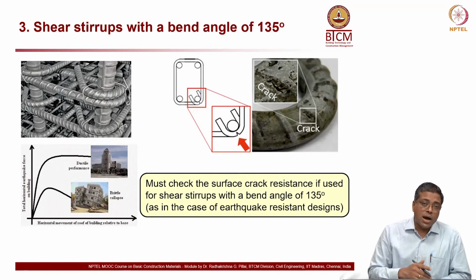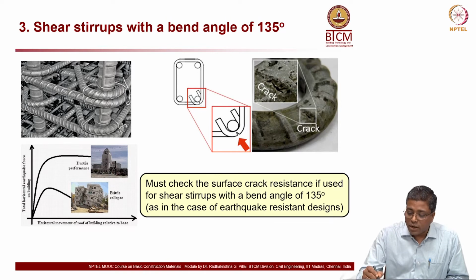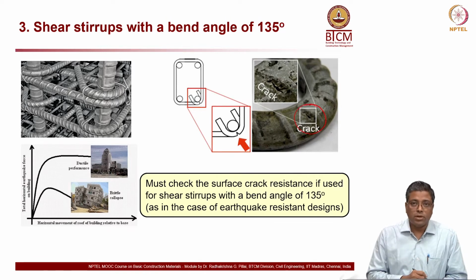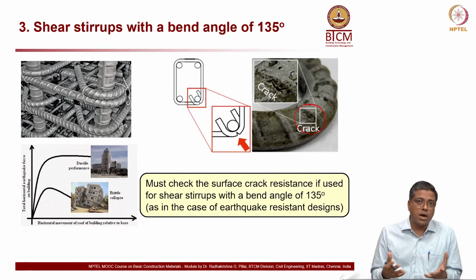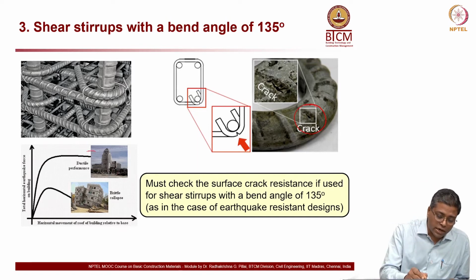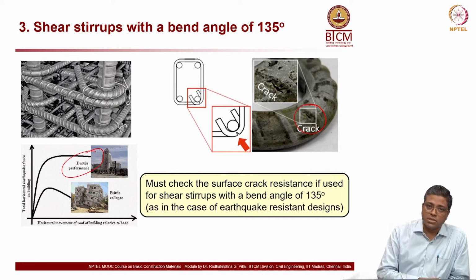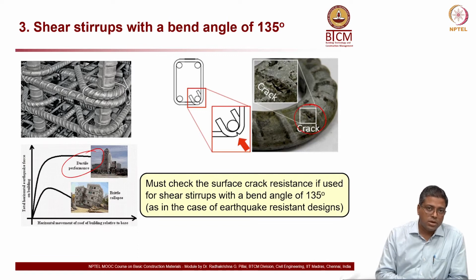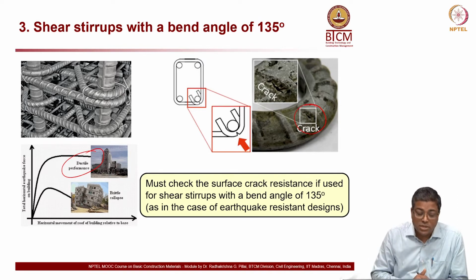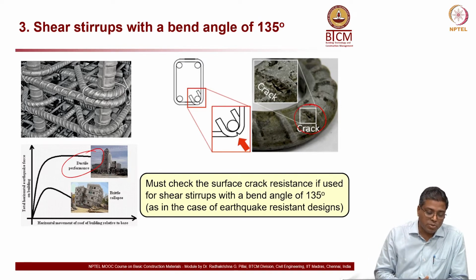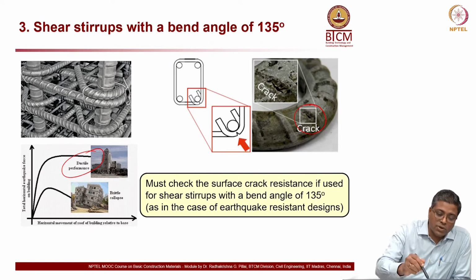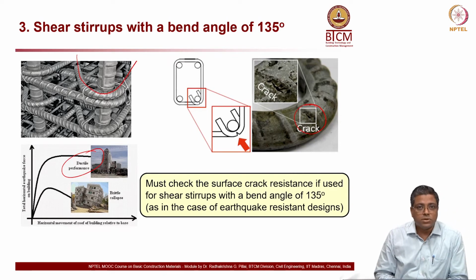Now we bend the bars at the site, and while bending, this kind of crack should not happen. Why do we use this bar? We use this bar for getting ductile performance for our structures. That is why we use TMT bars. The core region is more ductile, I told you, ferrite pearlite is more ductile. The peripheral region gives you the strength, which is tempered martensite. So the ductility is the key thing here. And for achieving ductility, we always bend these bars by 135 degrees.